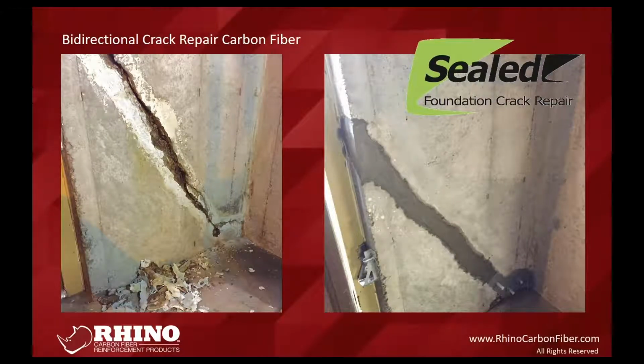And one thing that we love when our installers would do, and we train on it pretty heavy, is to do what we call a good, better, and best repair. And a part of that is the crack locks. So what we consider a good repair would be a crack injection as a standalone, or our carbon fiber crack repair as a standalone. A better repair would be those two combined, and the best repair would be a crack injection with the crack locks countersunk into the concrete itself, and then you have your carbon fiber crack repair, which is surface mounted.